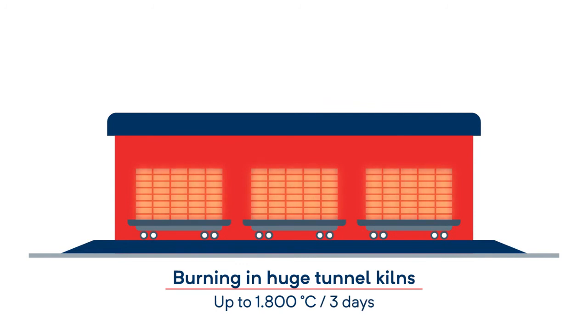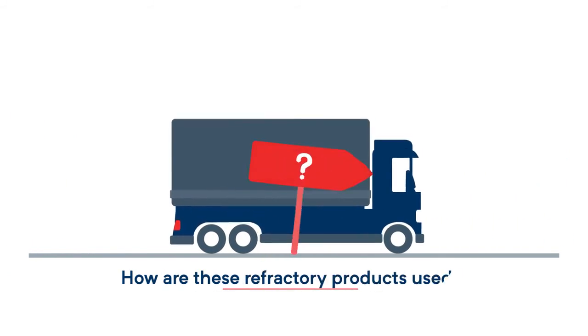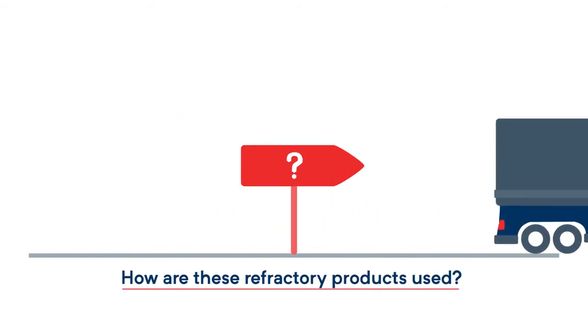Depending on the application, the refractory bricks are then tempered at up to 350 degrees Celsius or burned for three days in huge tunnel kilns at temperatures of up to 1800 degrees Celsius. And how are these refractory products used?